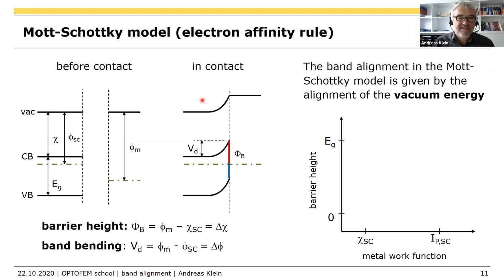Okay, what if this is what we would expect? If this is the real situation, we would expect that the barrier height varies with the metal work function in principle linearly. So if you increase the work function, you will increase your band bending. And the slope here would be 1. Of course, if your Fermi level is reaching the valence or the conduction band, it will hardly move anymore. So this is indicated by these lines.